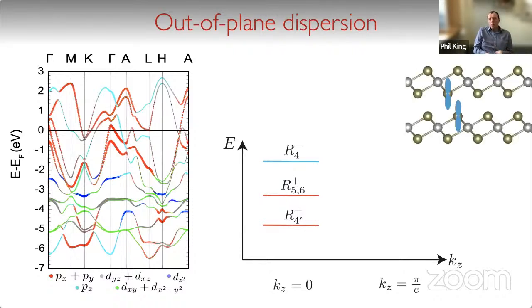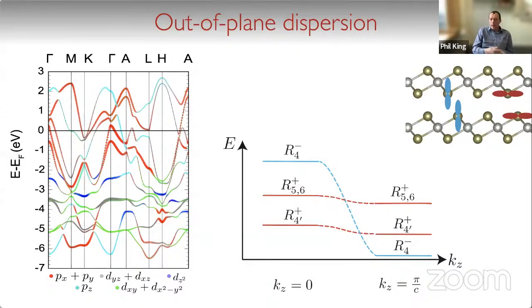Okay, so if we first think about these pz derived states, these are states with the lobes of the orbital pointing between the neighboring TMD layers. And so you can expect a fairly significant interlayer hopping coming from these pz-derived states. Or in other words, you'd expect there to be a large out-of-plane dispersion of the pz-derived bands along the gamma A direction of the Brillouin zone. Okay, if we think instead about the px and py derived states now, these are our planar orbitals. They're lying in the plane of the TMD layer. And so you'd expect a much weaker hopping of these states across the van der Waals gap. And so this should give us a much smaller bandwidth of these states as a function of the out-of-plane momentum.